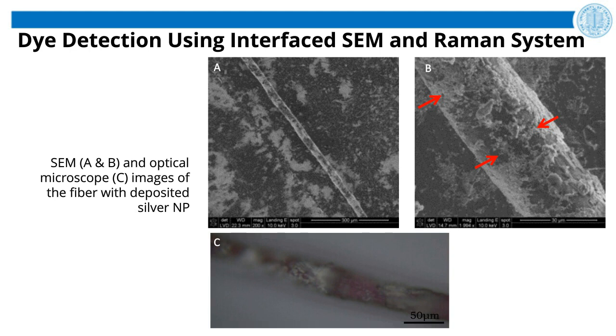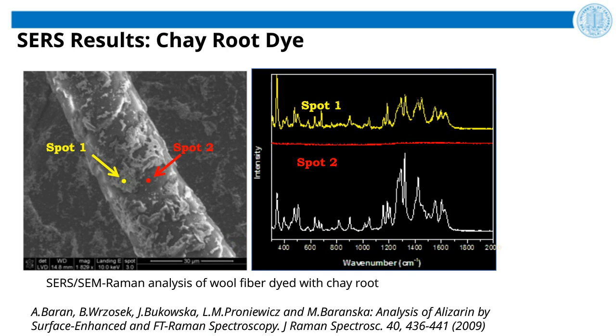This slide shows results of SERS analysis on the wool fiber dyed with madder root. The analysis of areas with thick layer of nanoparticles or without nanoparticles resulted in low signal-to-noise ratio or no signal at all. Areas with thin layer of silver nanoparticles led to optimal reproducible spectra characteristic of the dye molecules. And observed bands on the experimental sample at 1153, 1290, 1316, 1457 and 1617 are in good agreement with reference sample of alizarin, the main chemical compound of the madder root, and in compliance with earlier published results on the SERS of alizarin.